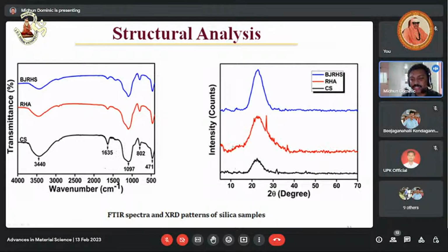And XRD analysis is also conducted. We could see a broad peak at 2 theta equal to 22 degrees that confirms the formation of amorphous silica. The blue one represents BJRHS, and in the red one and black one, apart from the broad peak at 2 theta equal to 22 degrees, there are some shoulder peaks. It might be due to some impurities, or some crystallinity in the material. So the broad peak at 2 theta equal to 22 degrees in BJRHS confirms the formation of amorphous nanosilica.